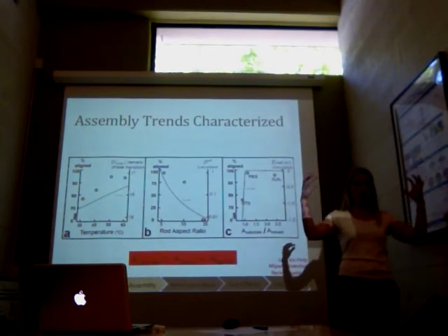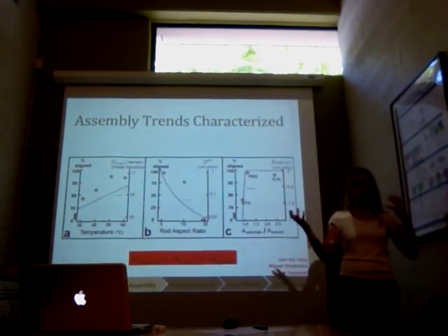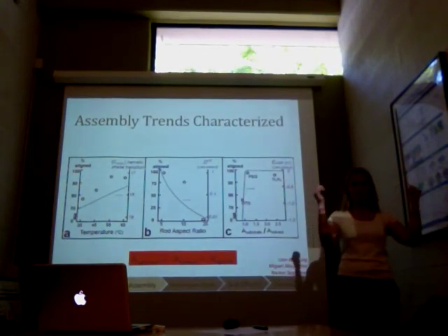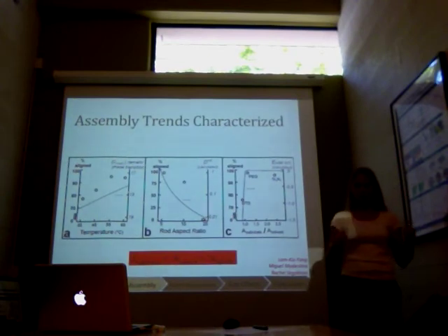So in order to align, we need them to be pretty concentrated in solution. That induces the liquid crystal phase transition. But if they're really long and then they're also concentrated, kinetically it's really difficult. They're interfering with each other. So we were kind of left at 40 nanometer length.